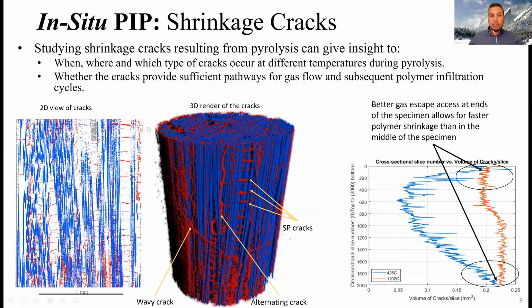But what becomes interesting is that you can evaluate whether these cracks provide sufficient pathways for gas flow during pyrolysis, and also whether they provide sufficient pathways for subsequent polymer infiltration cycles after this one cycle of PIP infiltration. Another thing to look at, from the cross-sectional slice number versus the volume of the cracks per slice, is that better gas escape access is expected at both ends of the specimen, top and bottom. This allows for faster polymer shrinkage compared to the middle of the specimen over here.